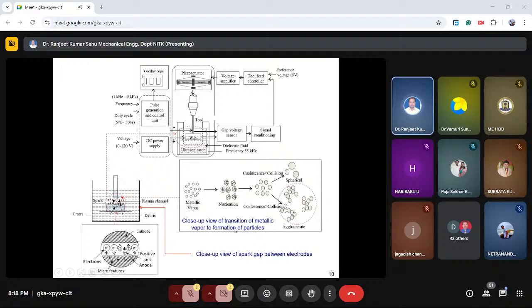This figure shows the close-up view of the transition of metallic vapor to formation of particles. You see, when the metallic vapor is ejected out from this molten pool, it starts to condense in the low temperature region, the dielectric medium, and it starts to nucleate in different orientations. Once the nucleation starts, this is followed by the growth of these nuclei in different orientations. Then this particle growth can be controlled by the physics behind the coalescence and collision rates. When the coalescence rate is less than the collision rate, we are able to obtain spherical sized particles. When it is more than that, at high particle concentration, then agglomeration starts to take place. This is the very basic phenomenon we have to understand.